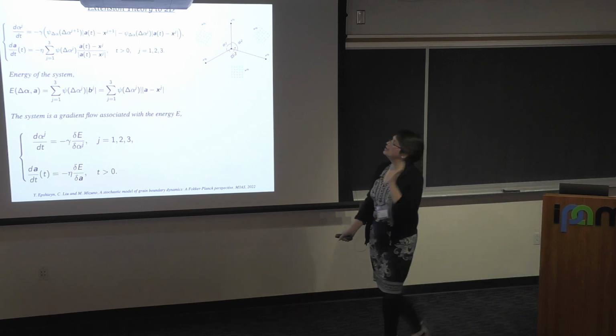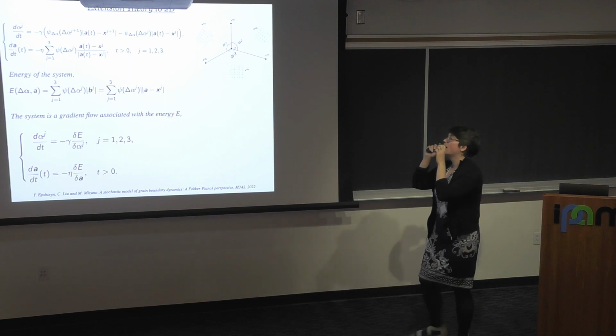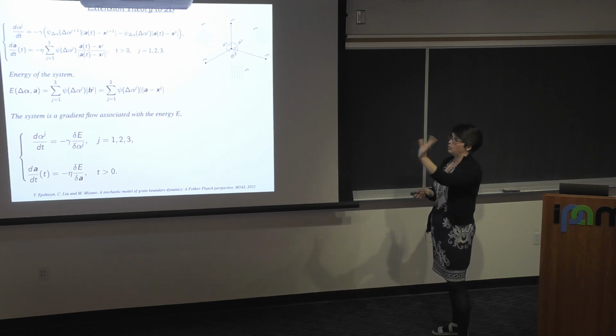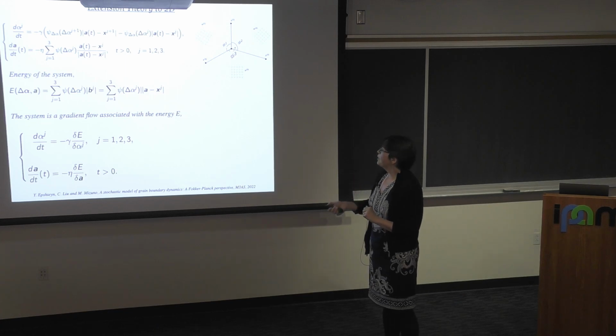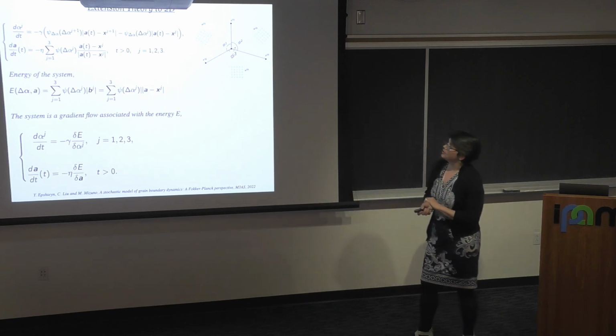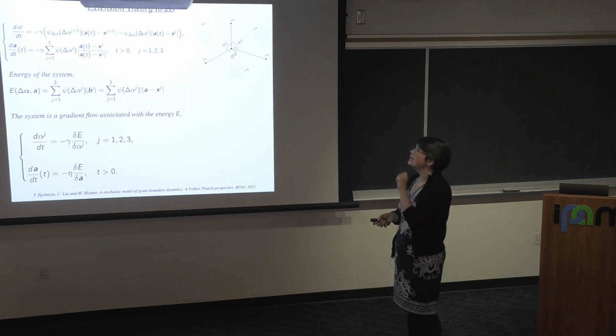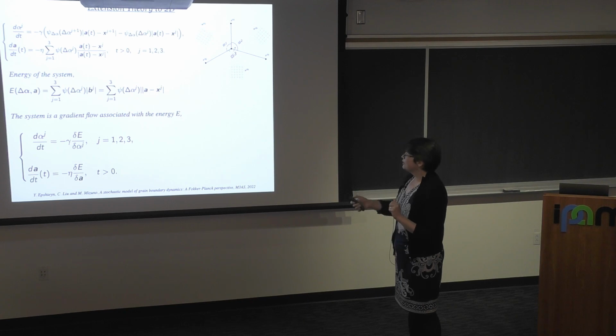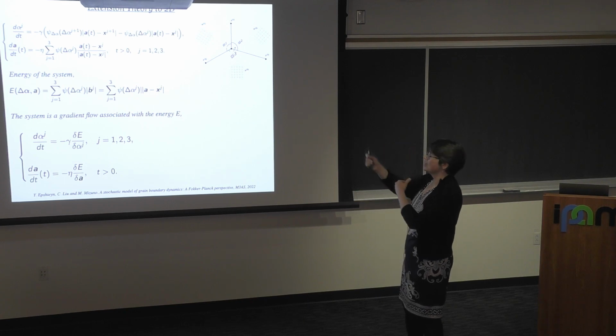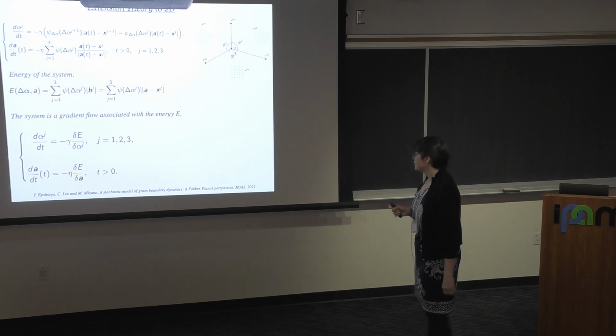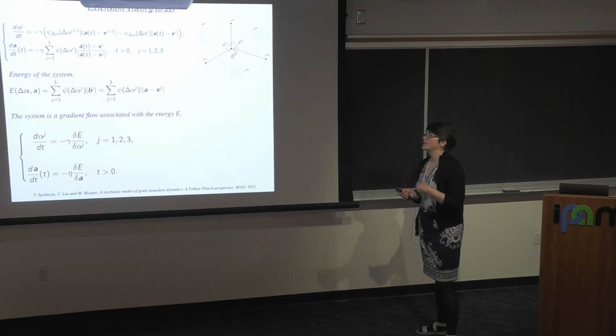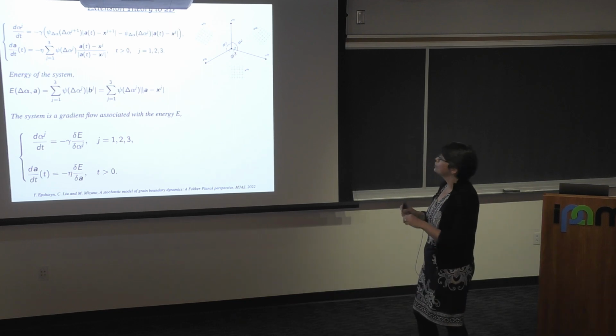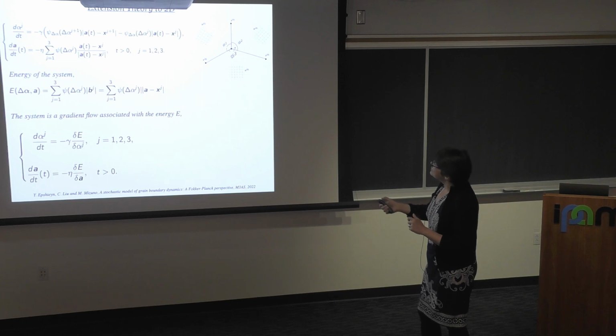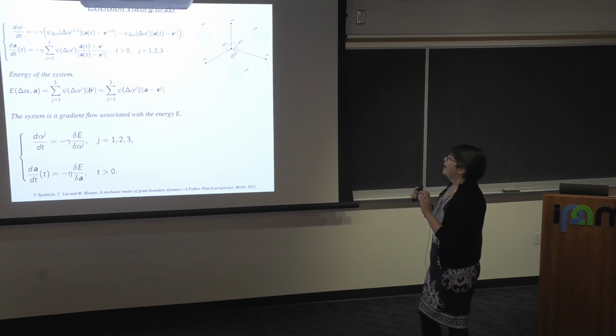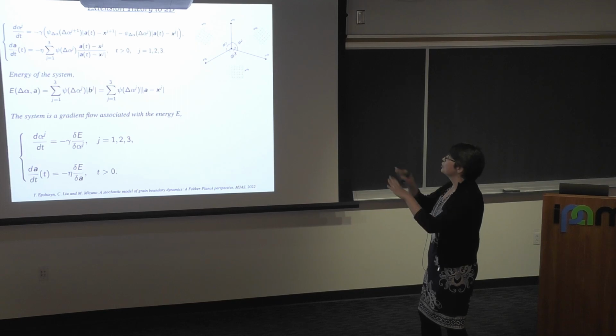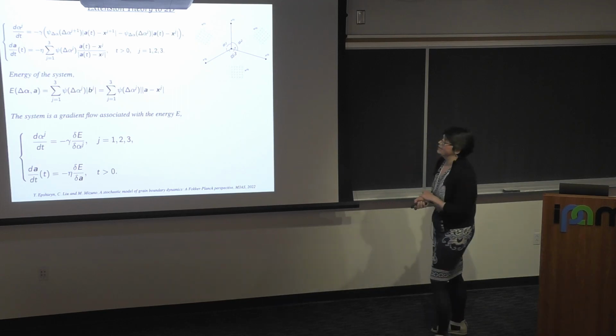And in our recent work, and that was the original goal at least, but once we started, we found this model that I presented earlier useful in many other aspects. We decided, can't we use this model that we introduced for the dynamics of misorientation or orientation and dynamics of triple junctions to try to extend that theory for grain boundary character distribution to a system that describes grain growth in a 2D cellular network more accurately.